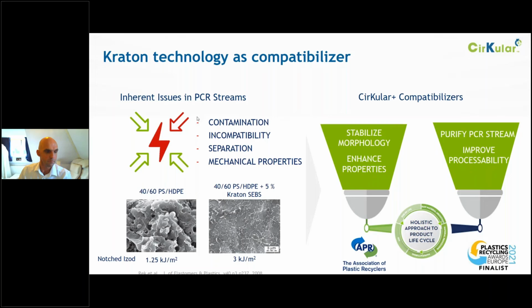There's contamination. For instance, if you want a recycled polypropylene, quite often there will be small amounts of polyethylene in there because it's technically difficult and then also economically unfeasible to completely separate them. There is some incompatibility between those two different types of polymers, which is impacting the mechanical properties. Even worse, if you have contaminants of maybe some biological fibers, metals, etc., it can actually lead to defects.